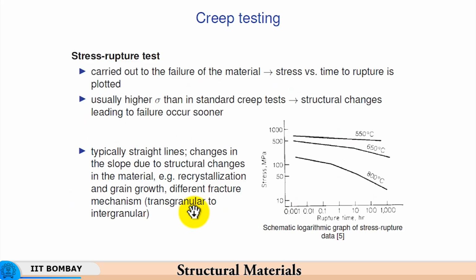Since creep is something that happens over a long period of time, we need to understand the properties within a reasonable duration of testing. A tensile test, for example, might last for say 20 minutes, 25 minutes, half an hour, but a creep test might last for several years. The creep strain which might be measurable can be generated over a long period of time of several months or several years. Since we do not have so much time to wait for the results, from an application point of view we need to finish the creep test in a reasonable period of time, and that is the reason why we need accelerated creep tests.